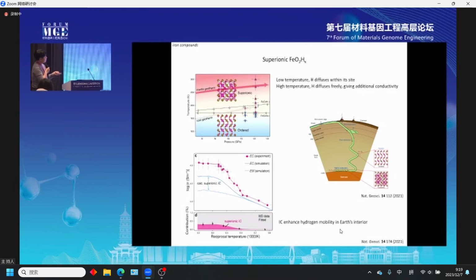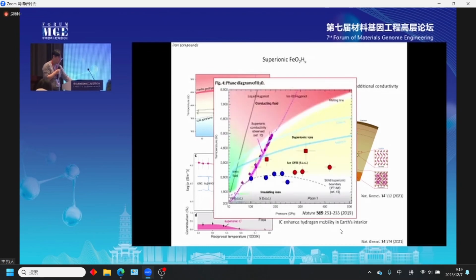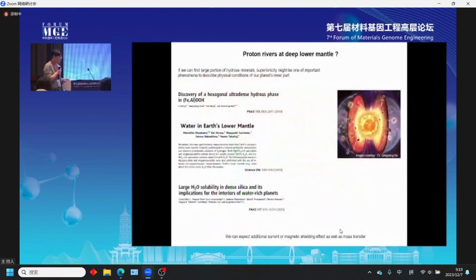This is reciprocal temperature, and this is conductivity. The conductivity suddenly increases in this pressure-temperature region, which exactly corresponds to where the superionic contribution happens. So this is the evidence of superionicity in our deep lower mantle. So we believe that in our deep lower mantle, the superionic state of proton dynamics happens. And in 2019, superionic ice was proposed. That one is about Uranus and Neptune, but in our case, we are talking about our planet, the deep Earth.